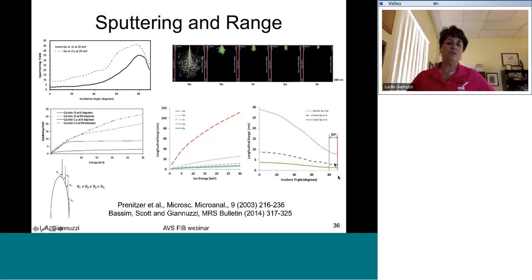So this means when we go to our low energy polishing considerations or low energy polishing routines, we can get away with hitting our surfaces at greater angles and not have to worry about increasing the damage very much. Also, if we take a look at this bottom left curve and match that with our sputter yield curve, we see that as the angle of incidence changes on a particular asperity or pillar, we're going to get different angles of incidence, and therefore we get different sputter yields. So this works out perfectly, for example, for making atom probe tips. You can take advantage of this, again, by cutting on an angle.